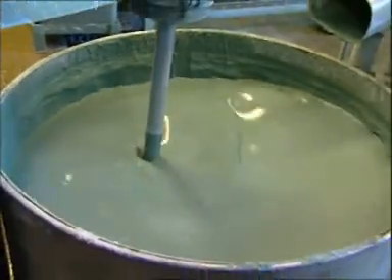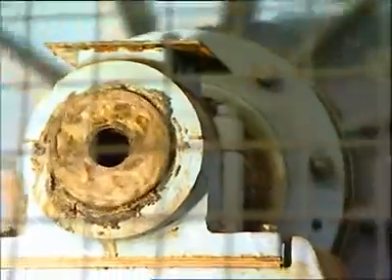The sheets are now flash dried, ready to accept the all-important pre-coat, which is a thin film of nickel-rich oxides and other chemicals, developed to create an enhanced fusion of glass to steel. This enables Permastore to use high-strength alloy steel in its structure design.